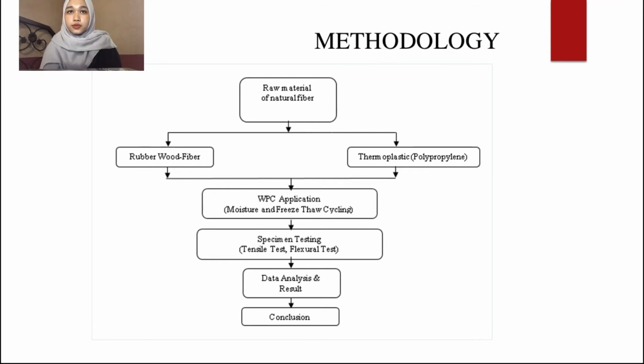After reaching equilibrium, half of the saturated samples will be exposed to freezing temperature. The flexural mechanical properties of all environmentally conditioned samples were obtained to identify the cause of damage, namely only moisture or combined moisture and freezing. Second, the constituent fiber and polymer mechanical properties of the rubber wood fiber plastic composite were experimentally determined through identification, flexural testing and mechanical tensile testing, and used as model input parameters.